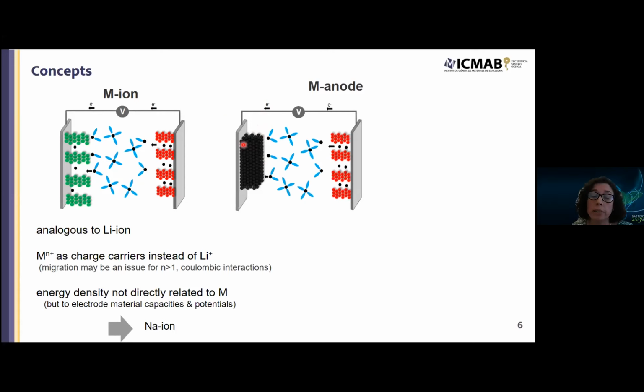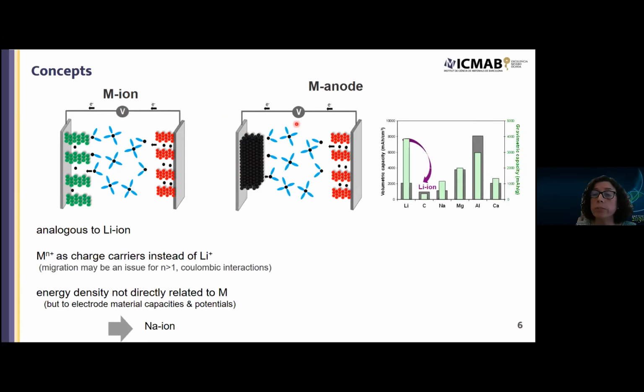And in this case, as you know, for lithium, there is an issue with dendritic growth, and there are a lot of efforts to try to solve this. But one could think of other alternatives. Here you have different metals, and you have the gravimetric capacity in green and the volumetric capacity in gray. Of course, nothing compares to lithium metal gravimetrically, but it's not very dense. And in any case, in lithium ion, one uses graphite.